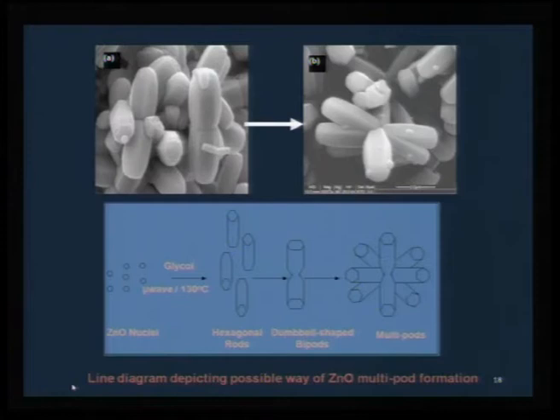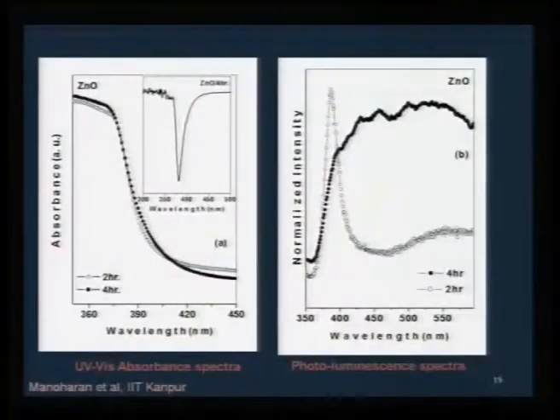This is one such view graph to highlight how zinc oxide can be made and how these are made as nanopods, and how exposure to microwave can influence the photoluminescent studies. For example, we have shown that if you just expose the zinc oxide for 2 hours in microwave, you get this characteristic 380 nanometer peak, whereas if you expose it to microwave for a longer time, at 4 hours, you totally kill this 380 nanometer emission, and what you see is a defect induced emission. So this gives a clear idea how the chemical synthesis has to be fine tuned and controlled, and how they can be very selective and specific in making materials of different composition.